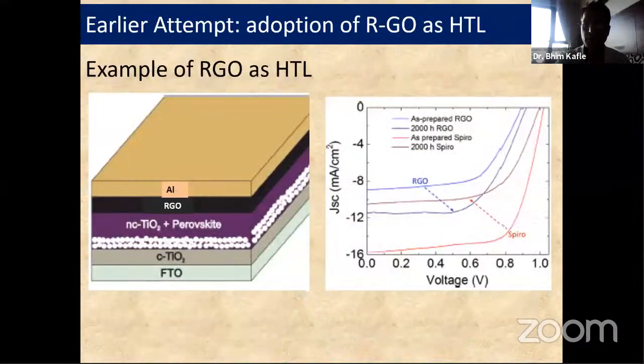For example, using spiro-OMeTAD has a poor performance and is less stable, while using reduced graphene oxide, you can see here the stability is larger. With, for example, 2000 hours of exposure to the sun and moisture, its performance degrades very largely with the organic p-type semiconductor, while with RGO it's a very small loss.